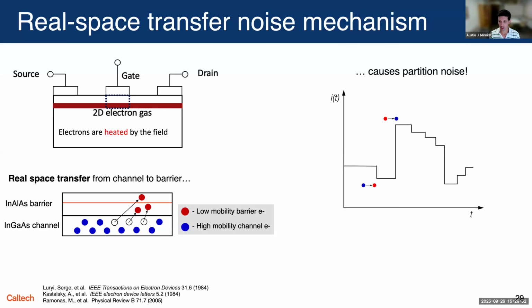So as a schematic example here, if a blue electron becomes a red one by hopping from the channel to the barrier, the conductance of the source to drain instantaneously goes down. And that leads to an instantaneous drop in the current. And vice versa, if an electron hops from the red barrier back into the channel, the conductance all of a sudden goes up. And so when you have these hopping events constantly happening, that manifests as a fluctuating conductance, which then is noise.